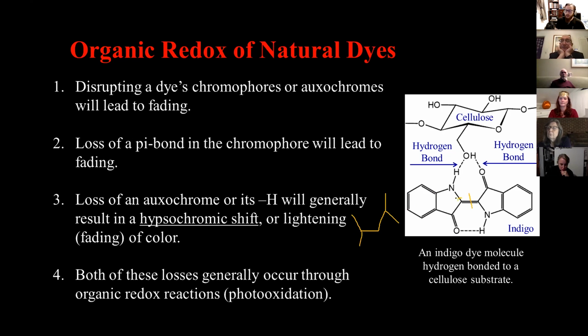If we just have this now, these carbons here would no longer be sp2 hybridized. They would no longer have those pi orbitals. So those would just have hydrogens attached to them, and it would just be a regular planar system like that. It wouldn't have those nice p orbitals over the top, so it wouldn't be capable of pi bonding. So that's what breaking a double bond in a conjugated system will do. It will lead to fading.